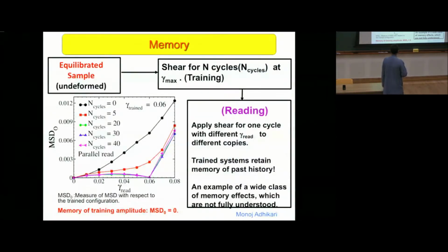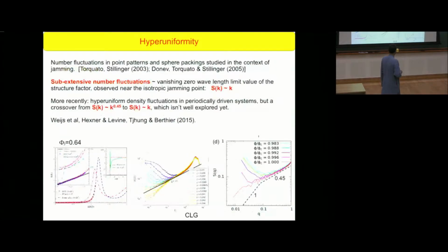Okay, so here is the signature plot of the memory. I've trained the system at 6% strain, and then I do a read cycle at an increasing amplitude of strain. What I find, if I look at the mean squared displacement at the end of one reading cycle, is that this mean squared displacement is 0 exactly at the amplitude at which I train the system, but below or above, it is finite. So this is a read-off which clearly allows me to tell something about the past history of the system, and therefore is a memory, okay? Lots of questions here, which I won't go into.